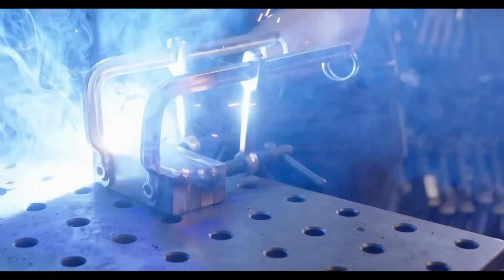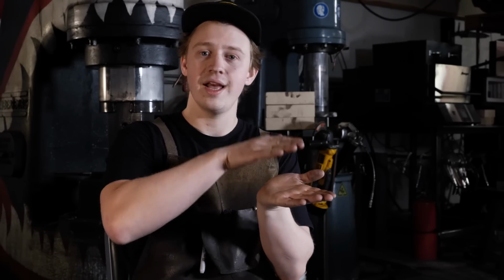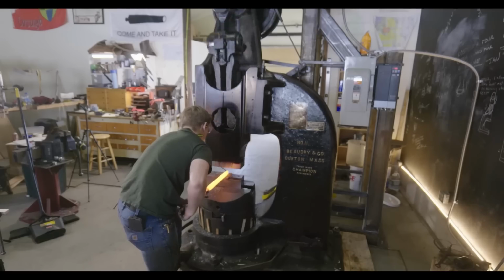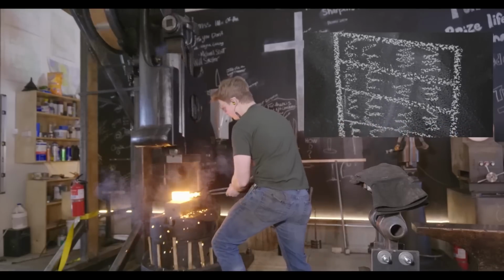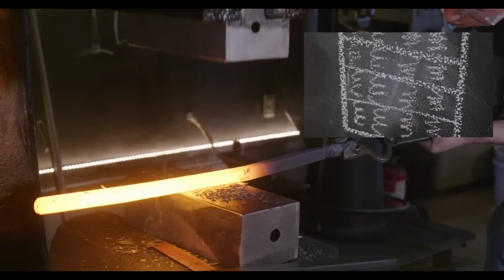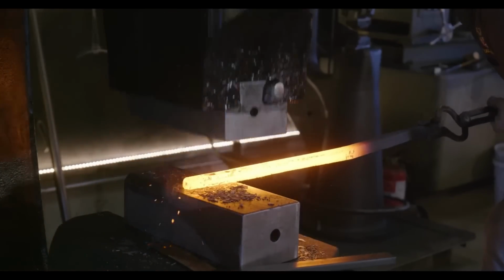Usually we'll bust through the tough scale with an angle grinder and then clean it up on a belt grinder. If you're blessed to have a belt converted surface grinder, that's another very efficient way to get through all that material. And then what you can do, if your billet is 24 inches long, you can cut it into 6-inch long pieces or 4-inch long pieces. And so if you cut it into 6-inch long pieces, you can take that 25 layers, you can stack it up 4 times. That means that you just went from 25 layers to 100 layers. All in one go, with a much higher chance of having clean, successful forge welds.